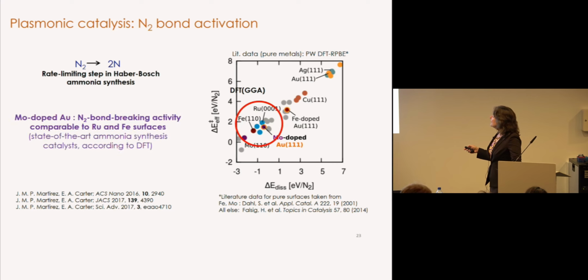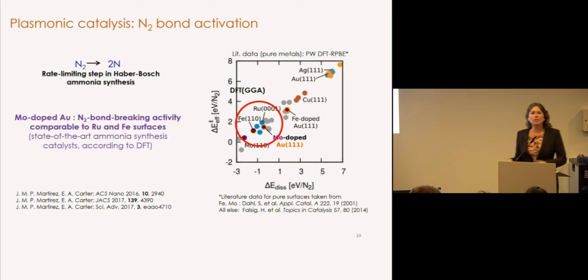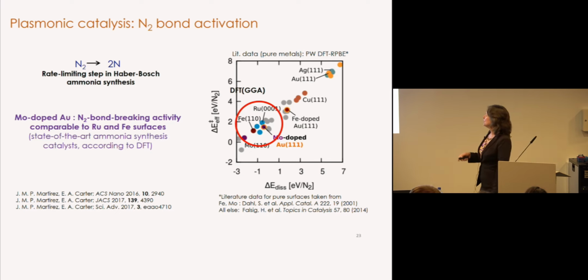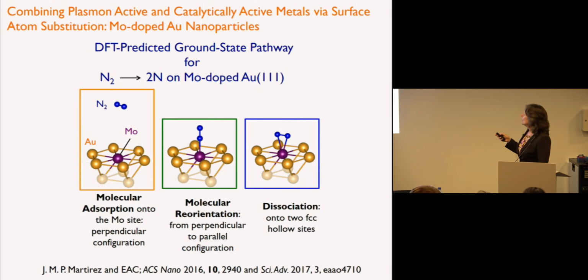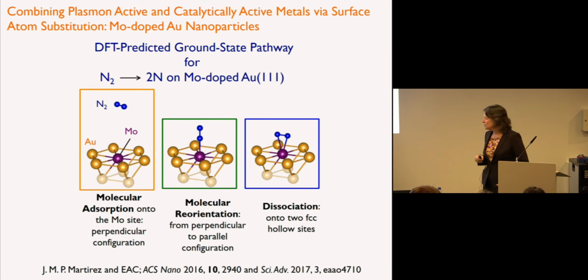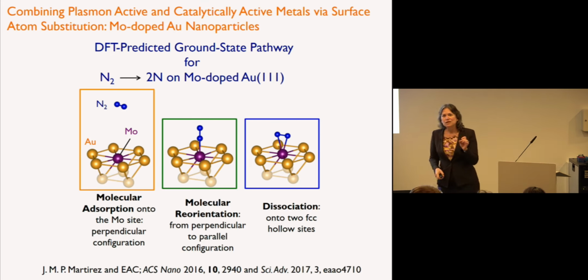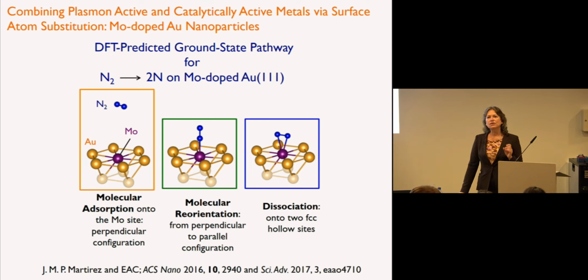And essentially, what we have shown is, even just at the ground state level, it looks like molybdenum-doped gold in particular falls in the same category with the most active metals that are known to do Haber-Bosch chemistry. So we wanted to look at molybdenum. What I'm going to show you is some of the results that look at these excited states and how we think this process is happening. And it's happening through a different excitation mechanism than the hydrogen case.